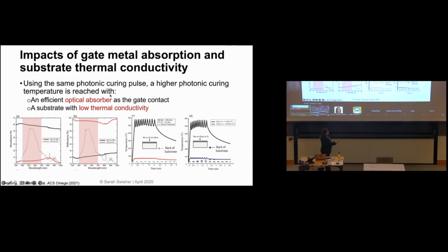And the other thing that matters a lot is the substrate. So here's another plot. Now both of these are going to be that molybdenum as this top absorber layer. But now we can say, well, I can put that molybdenum on glass, which has a low thermal conductivity. And I can see that I reach this temperature of about 500 degrees. The same molybdenum, the same size, the same illumination, if I put that onto a silicon substrate, I can't even reach 100 degrees. Why?